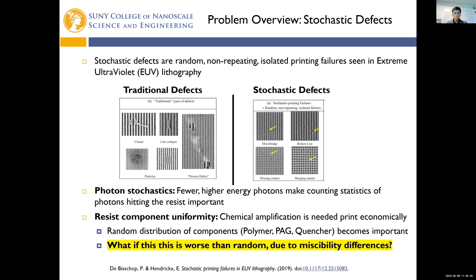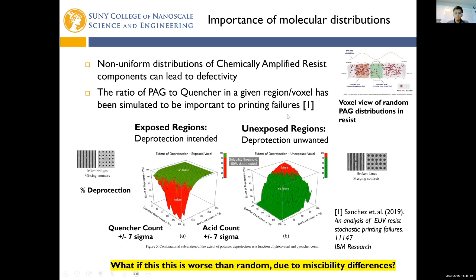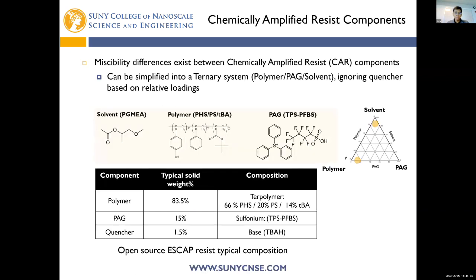Basically, you can have photon stochastics or resist component uniformity, which is what we were investigating. Basically, does the distribution of the components in the resist affect failure rates? And simulations have shown that you can get failure regions in the ±7 sigma areas for a particular volume of resist. And also, we know that miscibility differences exist based on chemically amplified resist components and the relative solubility.